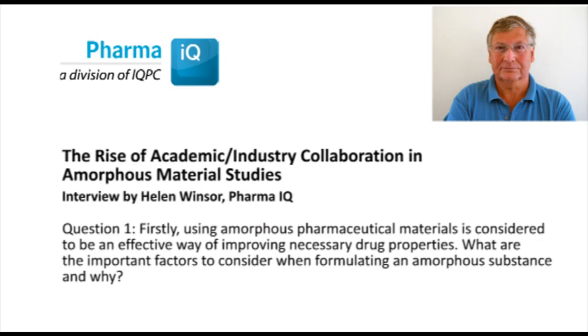Mainly, the amorphous state is an interesting formulation opportunity for poorly soluble drugs. That means when solubility is very limited in the crystalline state. So if you formulate in the amorphous solid state, which means glassy state, the solubility can be much higher. The drawback is that glasses are intrinsically not a stable state. They are prone to age, to recrystallize, and that cannot be avoided.